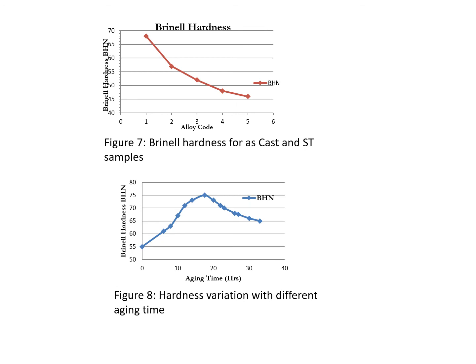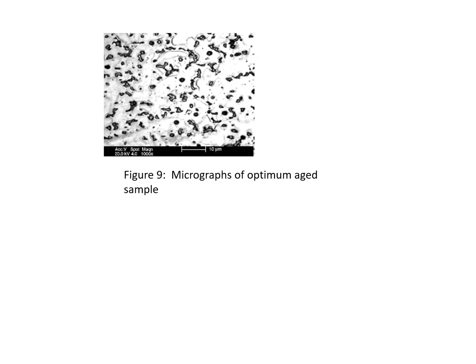Then effect of aging. The hardness values as a function of aging time at 180 degrees centigrade are presented in figure number 8. It is observed from this figure that the hardness increases with increasing the aging time and maximum hardness is found at 17 hours of aging time. Beyond that, it decreases. So figure 9 shows the presence of fine eutectic ternary phases distributed uniformly along the grain boundaries, which act as an effective barrier to dislocation motion, thereby improving the properties of ZA85 alloy.